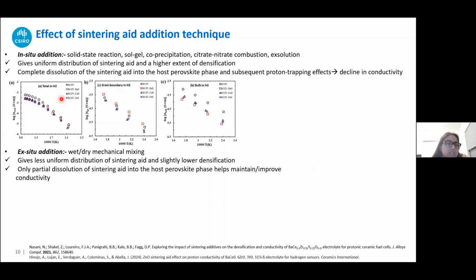So if you see in this figure, this is the total conductivity in hydrogen. The second one is the grain boundary conductivity in hydrogen. Here you can see they have used zinc, copper, and nickel, three different sintering aids in the same concentration, along with the bare mother material BCZY, and the grain boundary conductivity is very similar for all four of them. However, the bulk conductivity is higher for BCZY and it has dropped in the case of zinc, copper, and nickel, and that's because the zinc, copper, and nickel completely dissolve into the lattice and replace cerium or zirconium in the lattice. So that's not something which is quite favorable.